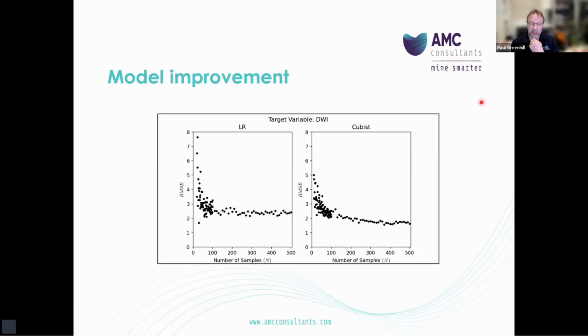So what we see is both models very rapidly improve before their performance stabilizes. The transition is especially sharp for the linear regression model, where the RMSE stabilizes at approximately 2.3, and there is no significant improvement when we include more than 100 samples in the predictive model training. The cubist model clearly outperforms the linear regression model and does continue to improve beyond 100 samples. And asymptotically, it approaches an RMSE of approximately 1.4.